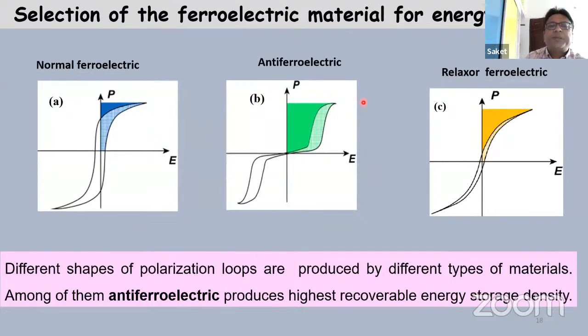So in the ferroelectric material, generally, if you see these loops, polarization loop, this is a typical ferroelectric loop. So only this blue portion can be utilized for the energy storage. This is anti-ferroelectric. Initially, it will behave similar to a linear dielectric, but at a particular field it will switch its domains, and then it will be a macro domain and behave like a ferroelectric nature. So this area is a good candidate for the energy storage.